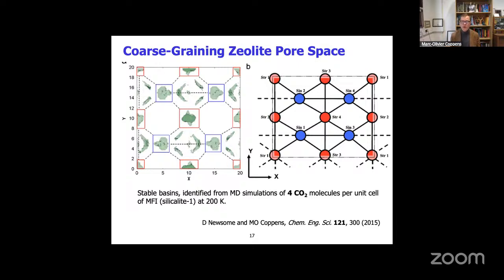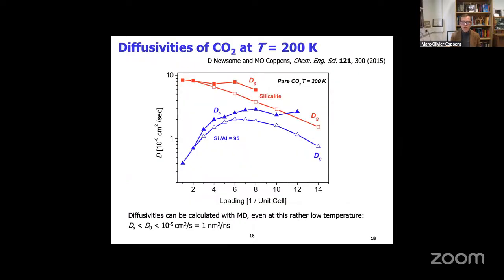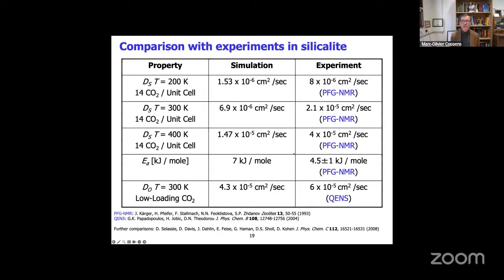So we have an effective coarse-grained network, and through that you can move from molecular dynamics via transition state theory, and invoke kinetic Monte Carlo and look at diffusion over much larger spaces. And then you can compare this with experiments. And we can look at both self-diffusivities and corrected diffusivities. These terms, for those who were there, have been introduced by Professor Jörg Kärger in a previous seminar already. And so they may be different, right? Because transport diffusion is not the same as self-diffusion. And so then we can compare these with experiments, and indeed using pulsed-field gradient NMR or quasi-elastic neutron scattering, find good agreement. Now, I show this example to show that in cases like this, we already have pretty good agreement